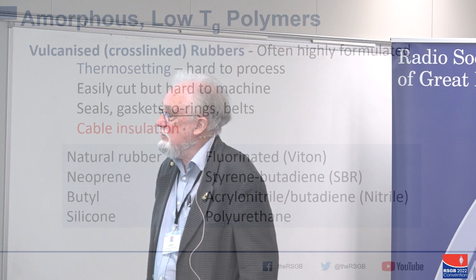But there are huge numbers of rubbers that have been developed over the decades. Natural rubber, neoprene rubber, which has chlorine in it and resists oil, butyl rubber for oxygen impermeability in inner tubes of cars, silicone rubbers for low temperature application, low temperature sealing and room temperature vulcanized sealants. Fluorinated rubbers for high chemical resistance. And then things like styrene, butadiene, acrylonitrile, ABS, all used for different applications, and polyurethanes.